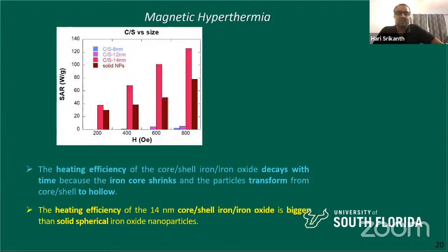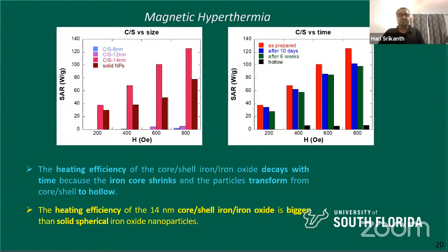Okay. All right, so let's look at the SAR, and I'm going to show you the results in histograms just for comparison, because with histograms you can compare different conditions. So this strategy of using a core shell particle indeed worked because of the larger magnetization of the iron core, the SAR. Remember, SAR is the heating efficiency that we measure using calorimetry or the other method, right? And you can see that in every case for different sizes, compared to the all solid iron oxide, the core shell particles definitely heat up much better.